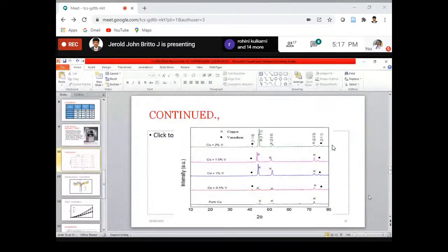Yes, sir. Actually, it is based upon the crystal plane, the orientation of crystals. How I have taken the values is that we have a JCPDS database. When we get the result, we normally get the peak at a certain degree, the maximum value. We already know that only copper and vanadium are there. So based upon copper and vanadium, we will know at which peak they will produce the maximum intensity. That value we check with the JCPDS database, and in that database there will be the crystallographic plane, at what angle the plane will be, the D value. So based upon that, for this particular theta, we find the crystallographic plane. Like that, I have plotted.